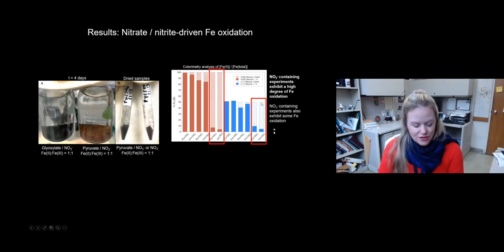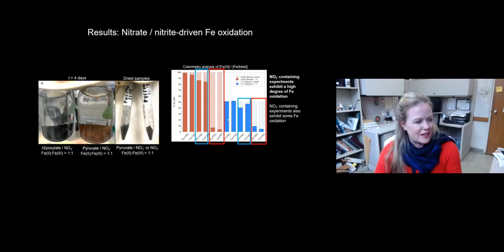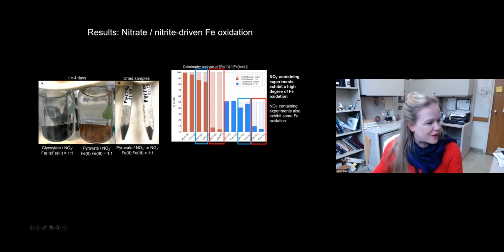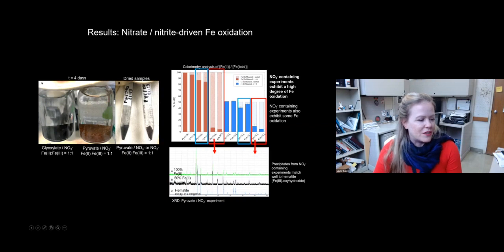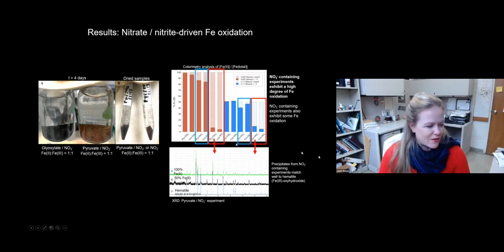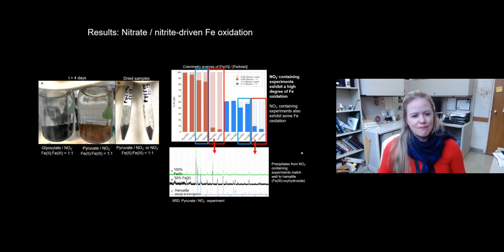We also observe that nitrate experiments do exhibit some iron oxidation. It's not nearly as much, but it's about, say, 10 to 15%. And then we analyzed the nitrite sample. So this one here, we analyzed with XRD. And we did this also from the 100% and the 50% Fe2 starting experiment. So it's both of these red boxes here. And so the XRD data shows that the samples match very well to hematite, which is a ferric mineral. So it seems that the presence of nitrite in these experiments is causing the formation of pretty much completely oxidized iron minerals. And the presence of nitrate is causing intermediately oxidized iron minerals to form.